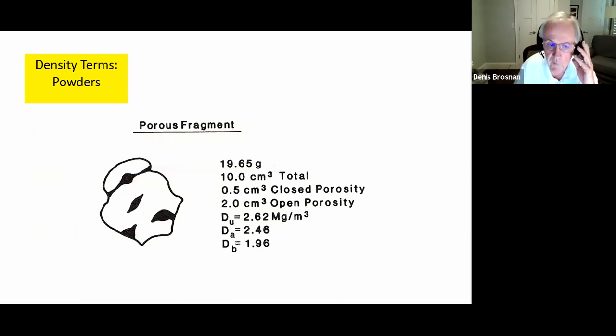Now, density terms also apply to powders. And here's an example of a porous fragment taken from one of the really good ceramic textbooks. And it tells us about the weight of the particle, the closed porosity, the open porosity, the ultimate density, 2.62, the apparent density, and the bulk density of the powder. So these terms apply both to fired goods and to powders that you might be using as a constituent of the ceramic.